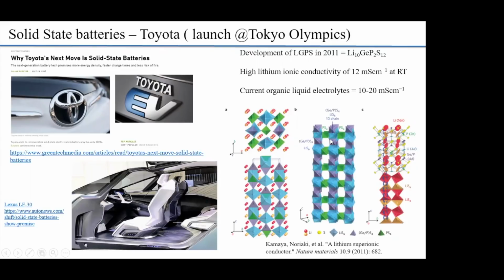In 2011, they developed this material called LGPS, lithium germanium phosphorus sulfide. And at that time, it was pretty remarkable because it had 12 millisiemens per centimeter at room temperature, whereas the organic liquid electrolytes have about 10 to 20. So basically you can look at this material as a huge building with multiple hundreds of rooms. And then there are hallways which are open for lithium to move. So this lithium can traverse from one end to the other because there's an open pathway, like in a building, long one-directional hallways, right? That is really conducive for lithium transport.